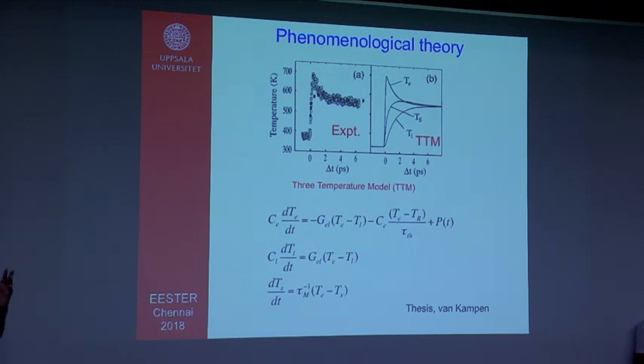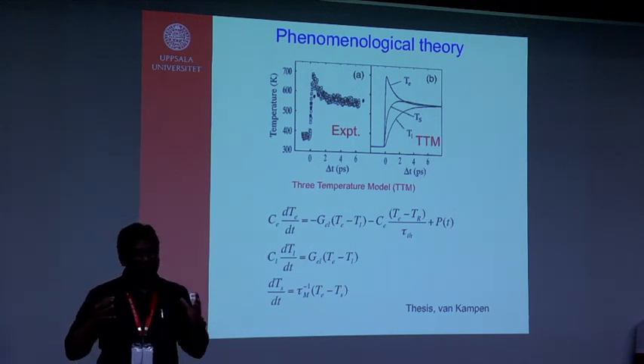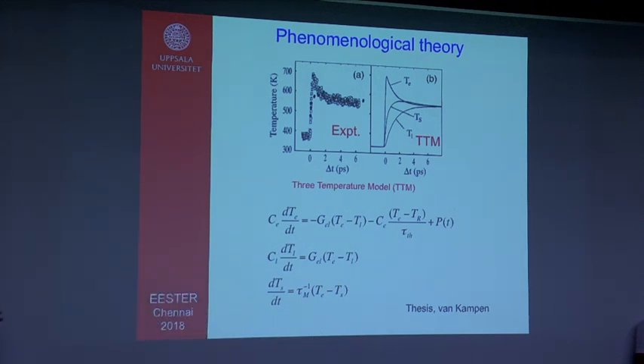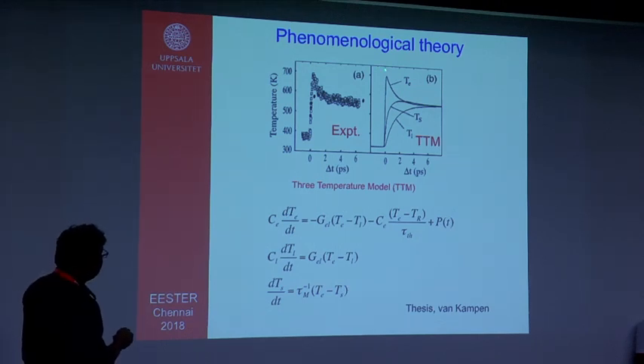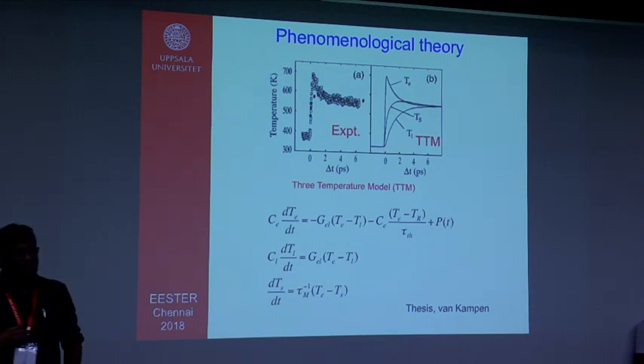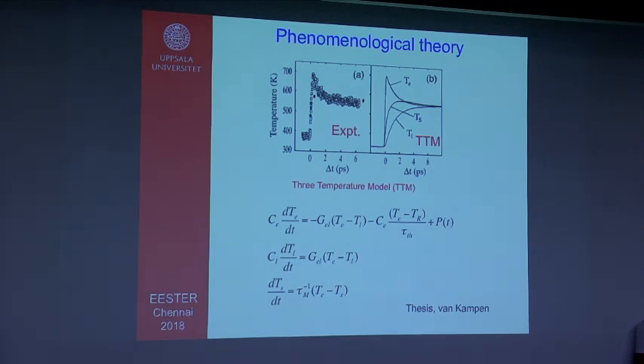Now you see that what happens is that when you shine laser on the system, the electronic system gets excited first. It becomes heated, it gets excited, and then it starts exchanging its energy with other subsystems. So you see that when the electron temperature goes down, at the same time the lattice temperature and the spin temperature go up. And finally, at a long time scale, they all merge together and the system is thermalized. So this is the phenomenological model which is actually used, and later on other people also used it, including us.